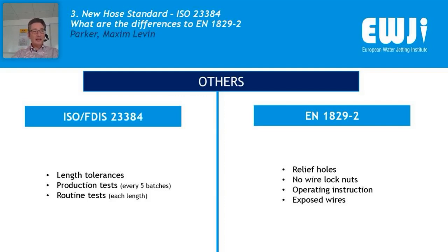In addition, it tells hose manufacturers not only how they have to qualify their hoses, which type tests have to be run with the hoses and fittings, but also which production or routine tests shall be done. That means, for example, that a burst pressure test shall be done on each manufacturing batch of hose assembly, which is already the case, because obviously the high quality hose manufacturers do verify their products, but it makes the quality requirements for the manufacturers a little bit more clear, more stringent, and more demanding.